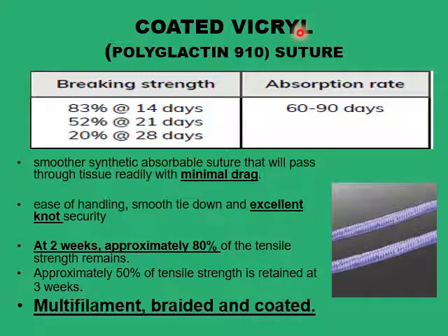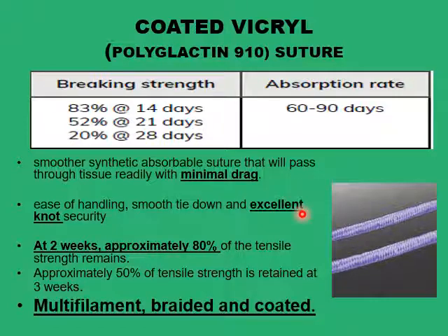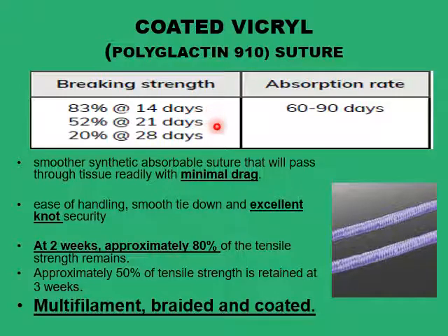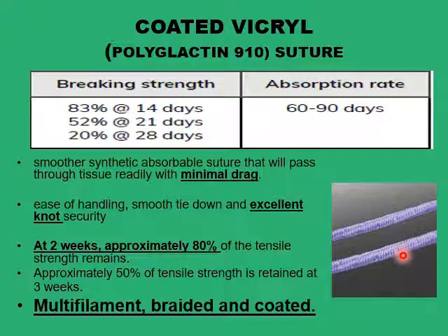When Vicryl sutures are coated, they produce sutures with superior handling properties, dragging with minimal friction inside the tissue and tying into excellent knots. They also retain most of their tensile strength at two weeks — about 80% of their tensile strength is still present at two weeks, 50% at three weeks, and even 20% after four weeks. They get absorbed completely within two to three months and can be braided into multifilament type sutures, which is why they have superior handling properties, enhanced further by the coating.